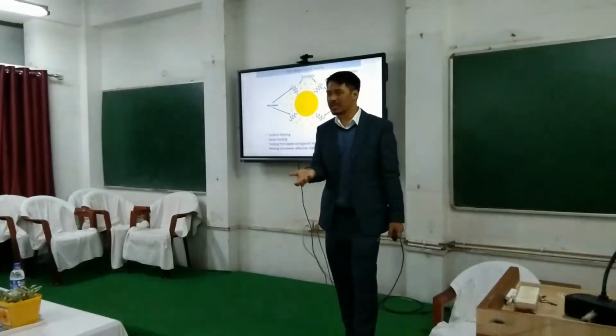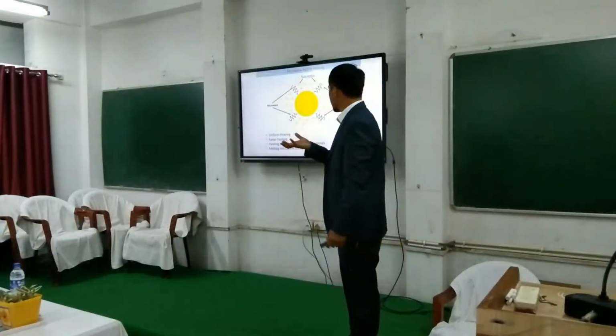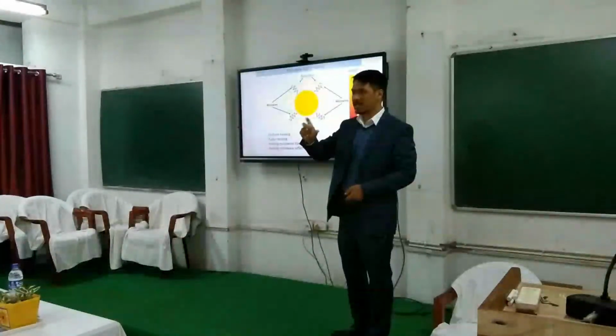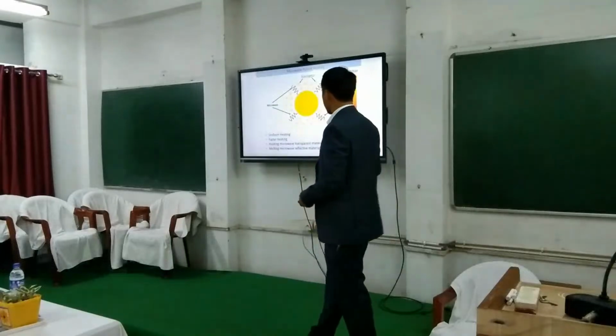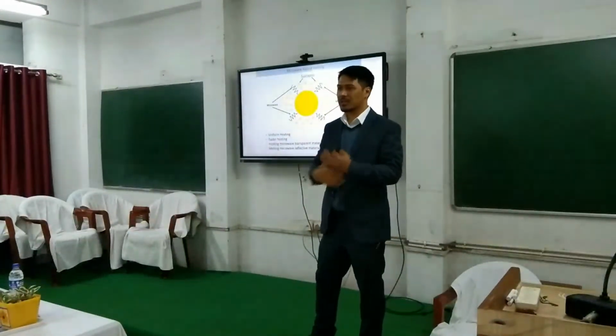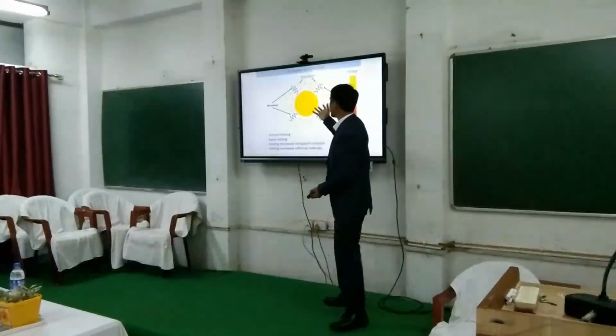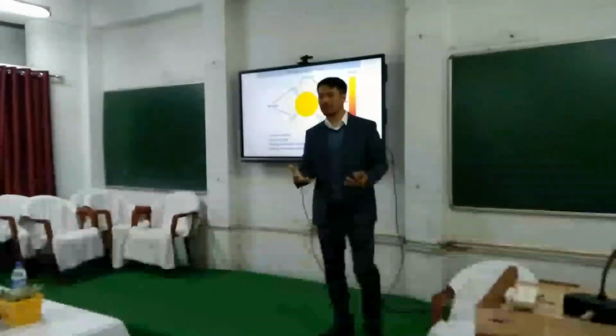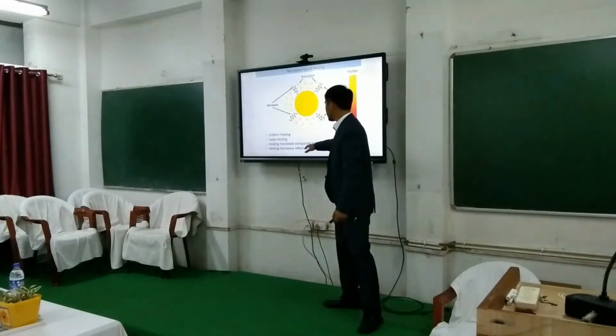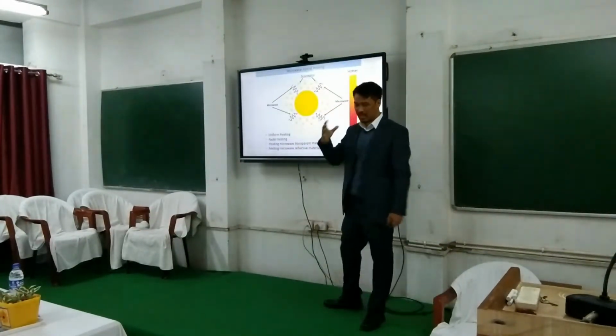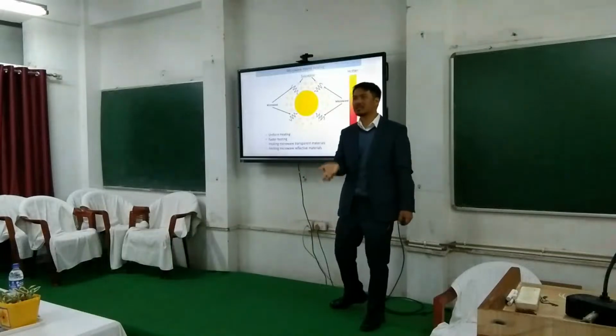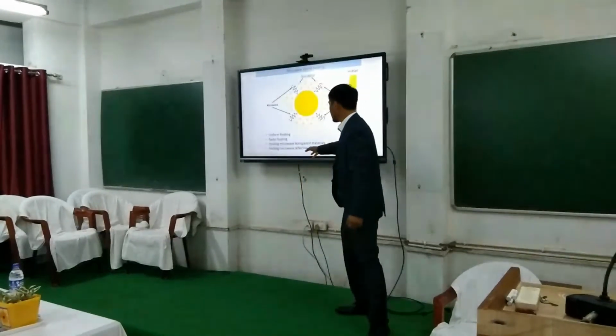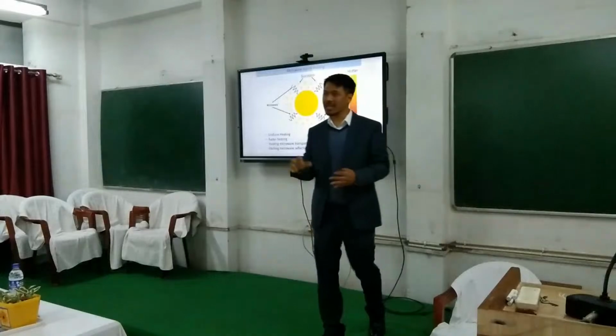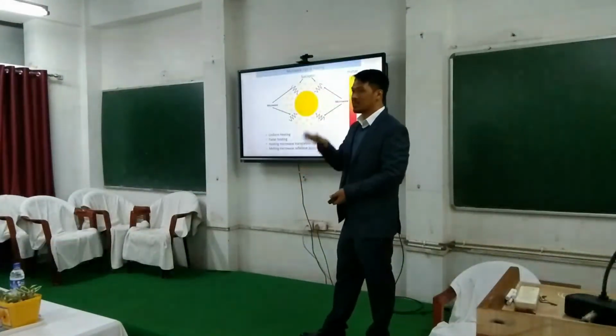Now, what happens is these transparent materials, if we increase their temperature, they will start changing the skin depth. The skin depth, which I told you, is dependent upon the conductivity. The conductivity and permittivity, all this changes with the temperature of a material. So with a change in temperature, the material starts becoming more absorbable for microwave because the skin depth is changing. That's how transparent materials are also heated up. Like ceramics can also be heated with microwave. Even metals which are fully reflective can also be heated with microwave, provided we increase the initial temperature.